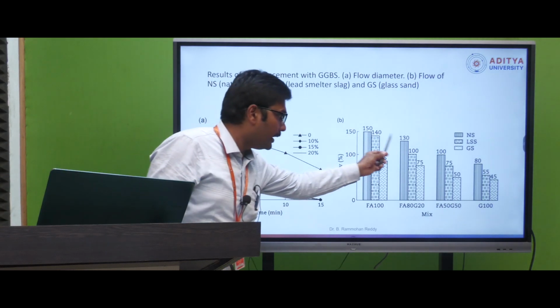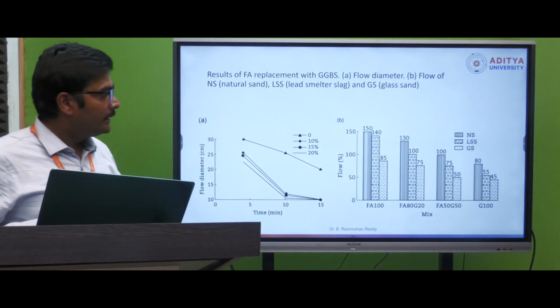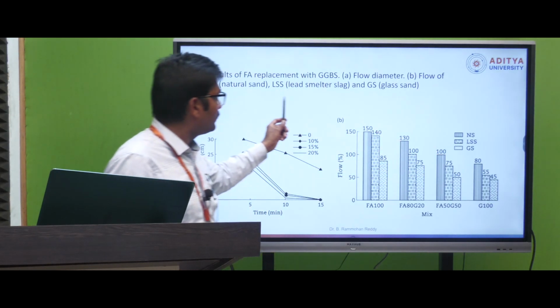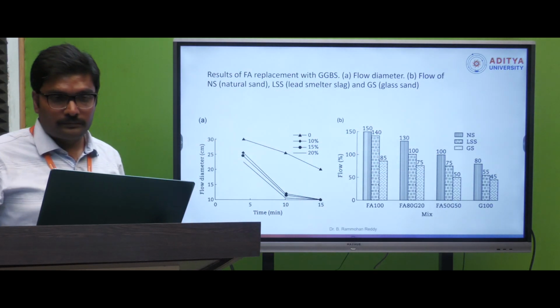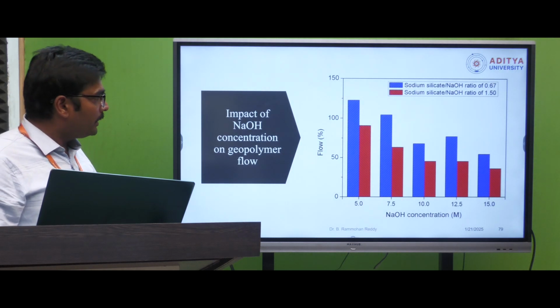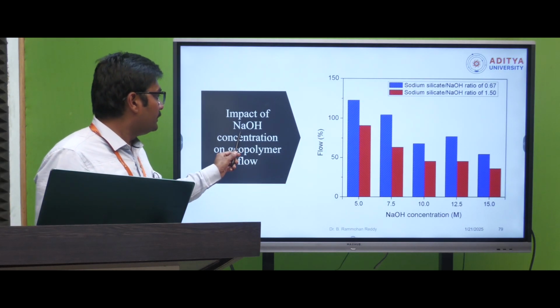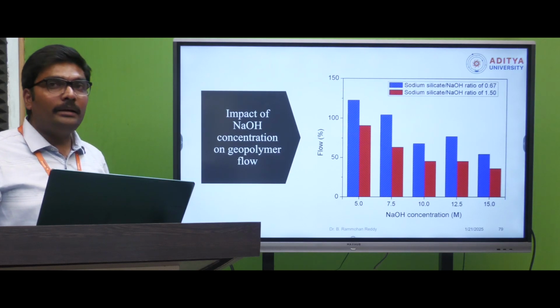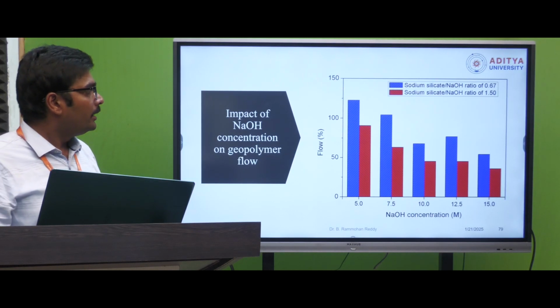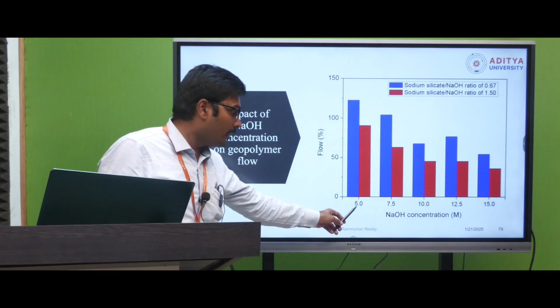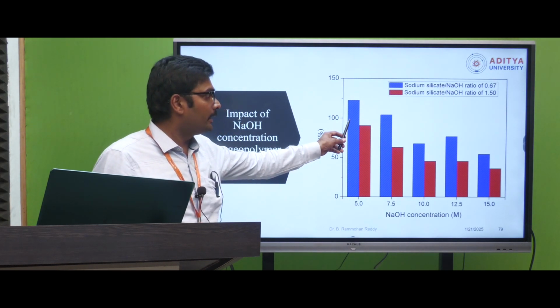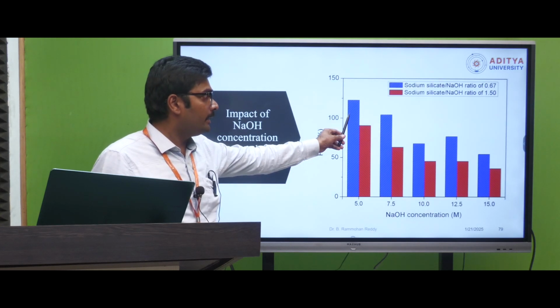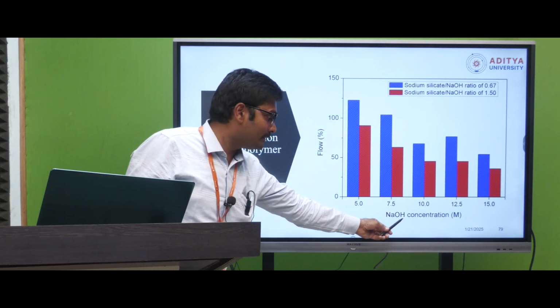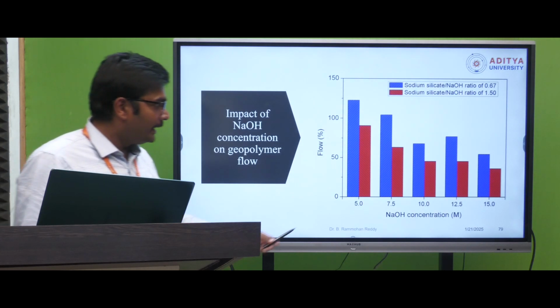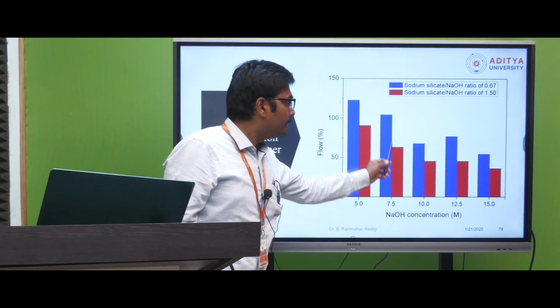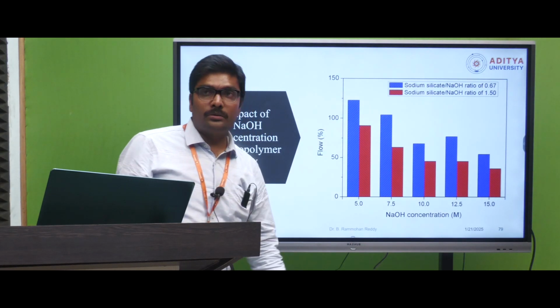That is what this diagram indicates. Here NS is natural sand, and LSS is lead smelter slag. And similarly for flow percentage, if you consider the NaOH concentration, the molarity of NaOH also plays a major role in the flow percentage. If molarity is 5, you can see a better flow percentage, and as the molarity of the NaOH solution increases, the concentration is high, and then the flowability is reduced for the geopolymer concrete.